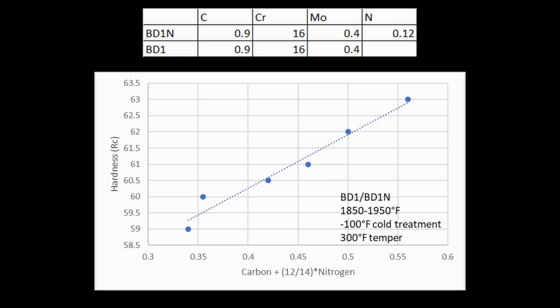And then I plotted out the carbon plus nitrogen versus hardness, and you get a pretty linear trend. You get more carbon and nitrogen in solution, you get higher hardness after heat treating. So it's all good news. When you look at this, you're like, okay, add nitrogen to everything. Yeah, I want it in every Pepsi.